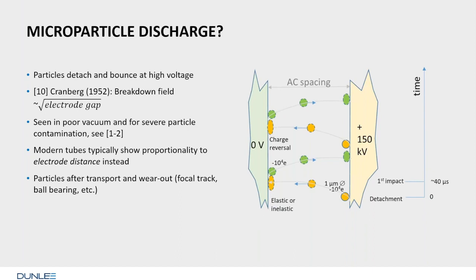One word about microparticles. As I said, microparticles can detach in vacuum. They sit on a surface with van der Waals forces, and you have to wipe them off if you want to clean the surface. But also electric fields can pull these microparticles off. Here you see a 150 kilovolts anode and a cathode at ground potential, and this little particle is charged. If it sits on a neutral or equipotential surface here, then electrostatic theory says it is charged. This one here has about 10 to the 4 electrons in it. And then this thing is, of course, subject to force. It's pulled off if it's large enough and the sticking force is not good.